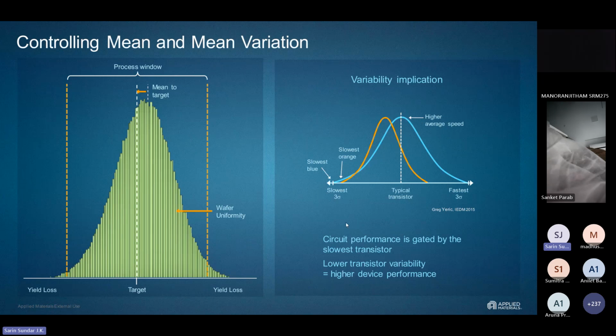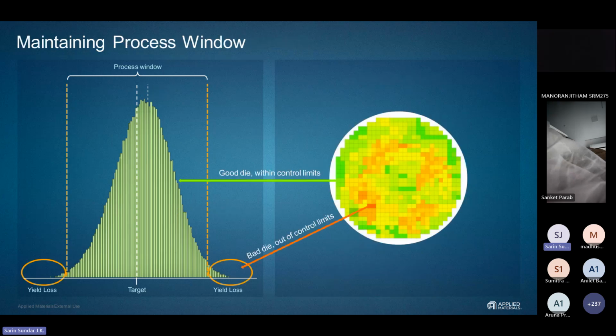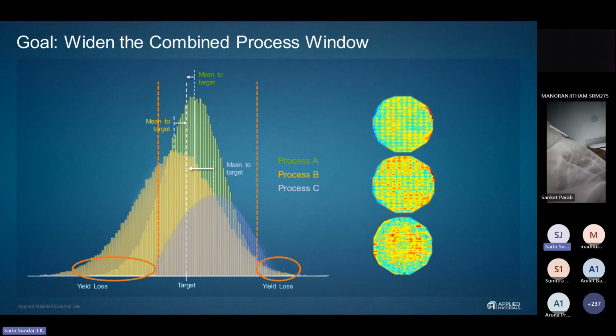How do you control the mean and variation in yield loss? I will not go through this in detail, but for example, how you interpret this. You can see here anything beyond that 6 sigma in the corner. Those are all the defective areas, the yield loss. Either it is too green or too high in red, based on whatever specification is given for that particular process. So if you want to maintain the process window, you can clearly define the yield loss from here. And if you want to widen the process window, you have your target, and you can also see if your process is shifting.